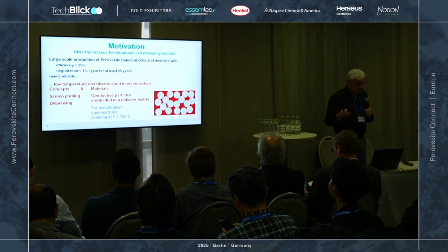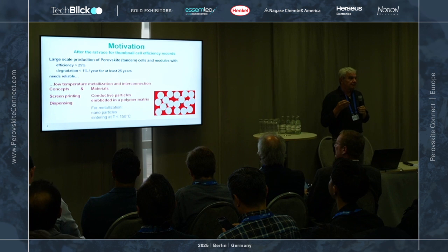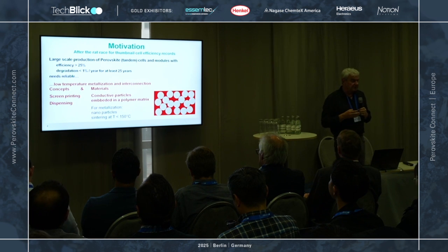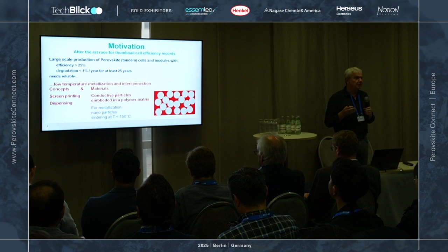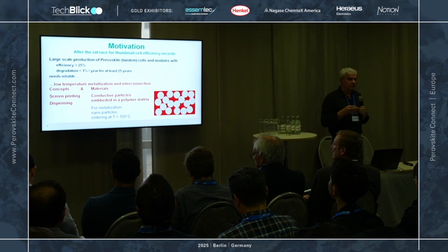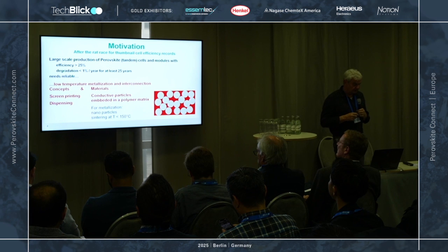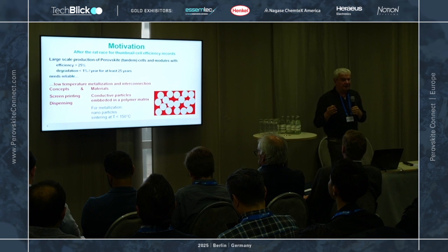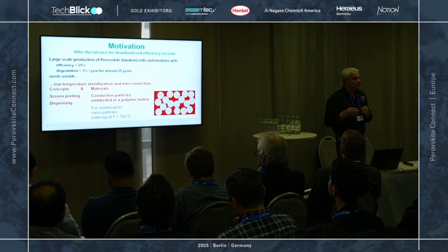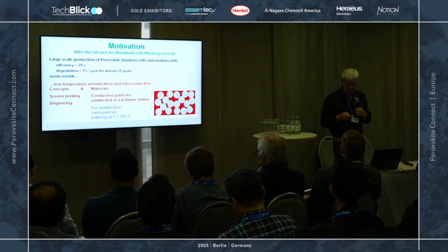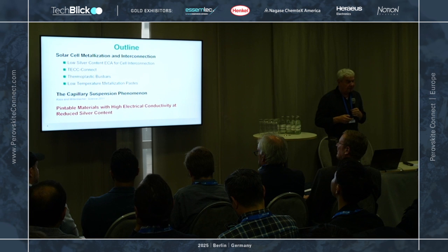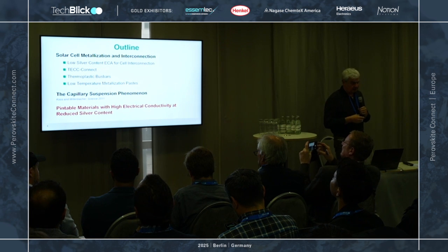And regarding the materials, you need conductive particles, conductive fillers embedded in a polymer matrix. The polymer matrix provides the adhesion to the cell and provides the cohesion within the metallization line or interconnection line. And for the metallization, you additionally will need nanoparticles because you want to have sintering to achieve a high conductivity at low temperature.